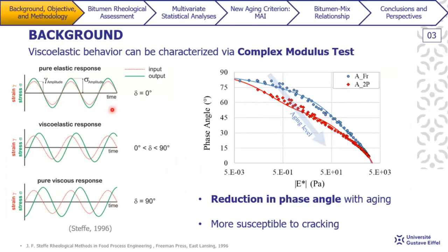So frequency sweep tests show that for a pure elastic response, there will be no phase lag or time lag between the loading and the response sine curve here, which in this case, our phase angle will be equal to 0 degrees. And on the other hand, we have a pure viscous material, where we're gonna have 90 degrees of lag between the loading and the response. And in between, we find all the viscoelastic materials like asphalt materials.